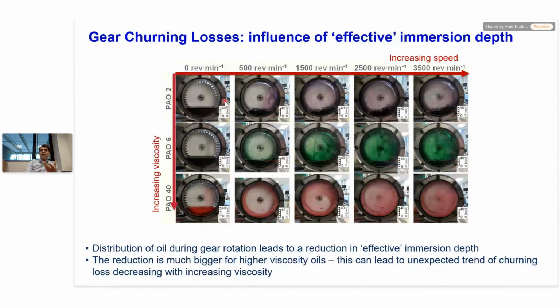So if you look at this effective immersion depth for low viscosity PAO2 oil at high speed, it's quite similar to the initial fill. If you look at the high viscosity oil, that was the initial fill, but look at it here. Your effective immersion depth is very, very small. It's almost zero. What that means is that you're actually going through a smaller amount of oil, a smaller depth of oil, and that reduces your churning losses.